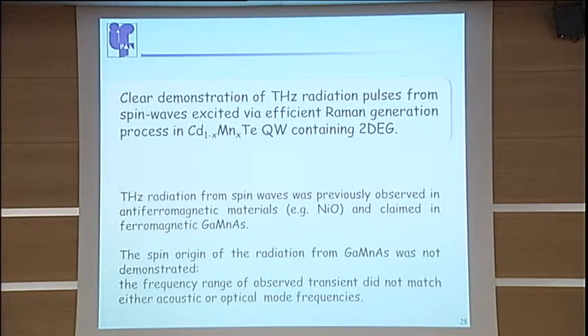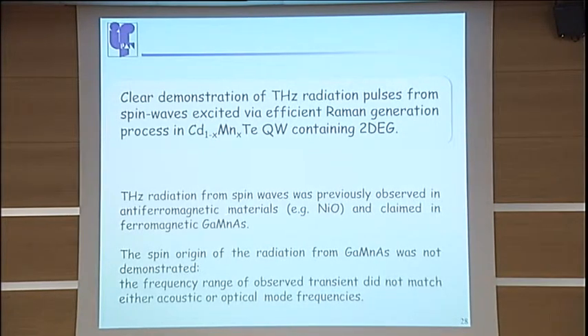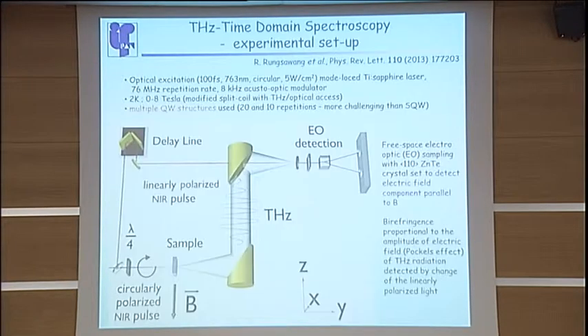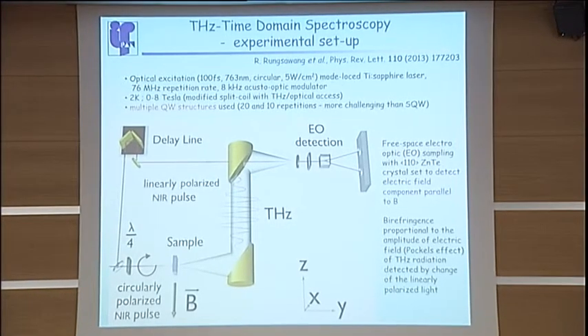Terahertz radiation from spin waves has been observed already in antiferromagnetic materials like nickel oxide. However, the claim that it has also been observed in gallium manganese arsenide was not that strong, because the frequency range of the observed transient did not match the mode frequencies of the material. Okay, so the experiment has been done like this. They have used a titanium sapphire laser.